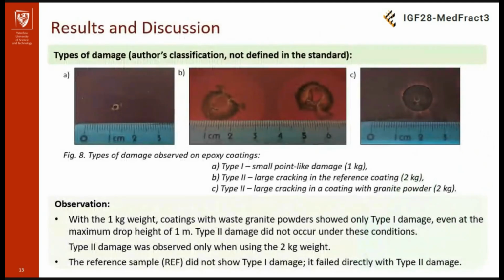Moving to the results, I observed two kinds of damage. With the 1 kilogram weight, coating with waste granite powder showed only type 1 damage, even at the maximum drop height of 1 meter. Type 2, so the larger one, did not occur under these conditions. Type 2 damage was observed only when using the 2 kilogram weight. The reference samples did not show type 1 damage at all. It went directly from cracking into type 2 damage.